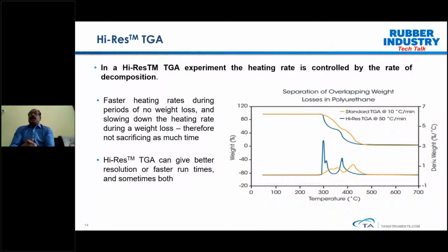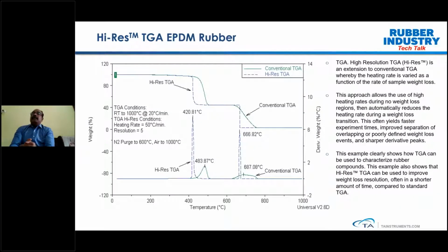Now, I could show you a simple EPDM rubber high-res TGA plot. So this is again what you can see here. The green curve is a conventional TGA where you'll be heating at a standard ramp rate of 20 degrees centigrade per minute. Coming to the blue curve, which is high-res TGA, you can see the derivative peaks look very sharp, and that is because of better resolution.